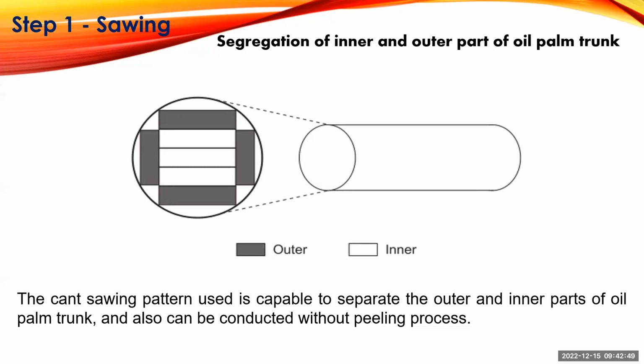So the diameter of the palm tree must be more than 30 centimeters. The palm is then sawn to obtain palm lumber using a sawing machine, with a thickness in the range of 2.5 cm to 4 cm. This palm trunk is cut or sawn according to the modified cant sawing pattern.